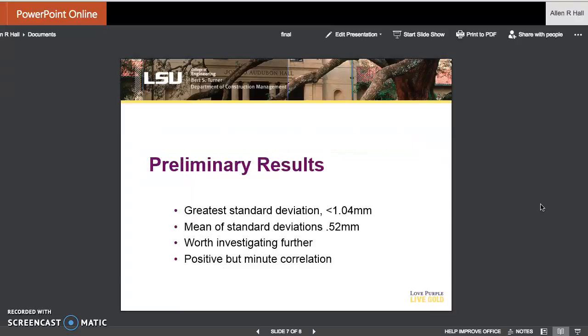So the preliminary results are very interesting. They show the largest standard deviation from flatness was a millimeter. That meaning that within the different samples, none of them were further than a standard deviation of right around a millimeter different. So our gut initial feeling is that these all turned out pretty much the same. The mean of the standard deviations was only a half mil, so everything turned out pretty much the same. There was very little shrinkage, or difference in shrinkage.